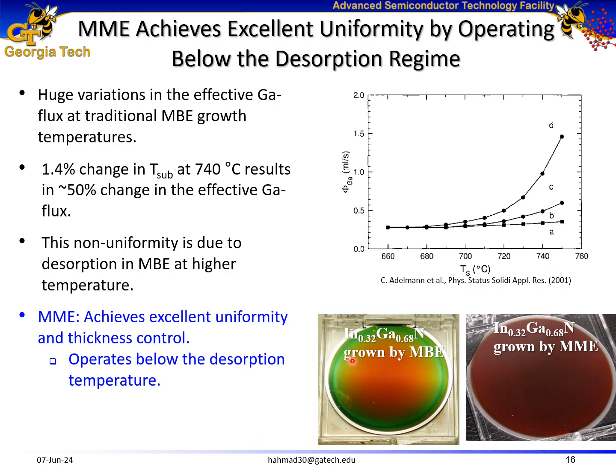In traditional MBE, we observe huge variations in the effective gallium flux. For example, in traditional MBE at a substrate temperature of 740 degrees C, a 1.4% change in the substrate temperature would result in a corresponding flux change of approximately 50%. This non-uniformity is due to desorption in MBE at higher growth temperatures. MME, on the other hand, achieves excellent uniformity and thickness control because it operates below the desorption regime.